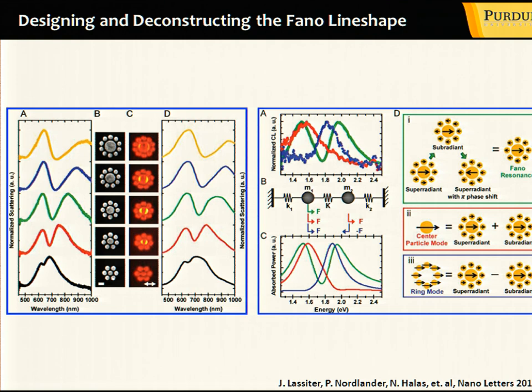This recent work comes from Naomi Halas's group, which shows that you could control these basic characteristics of the Fano resonance by using a cluster of metallic particles, and by changing the separation between particles and their sizes, you could really accomplish whatever you want in terms of the magnitude of this Fano resonance and its position. A very important feature here is that by exciting these plasmon modes with electron beams, you could excite them locally, because this Fano resonance is always kind of an interference effect.